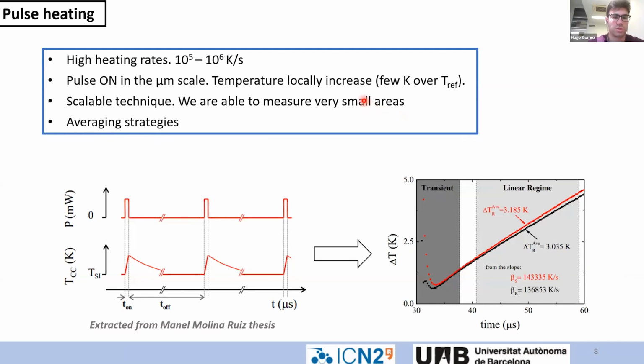I'm going to present a little bit about the technique that I told you, the pulse heating technique. It was developed in the group back 10 years ago, and right now we are using it again in order to measure these materials. We can have very high heating rates, something really important in order to have very high sensitivity. I didn't explain what the pulse heating technique is. In this technique, what we have is a very short pulse, on the order of the microsecond scale, with a very high current.